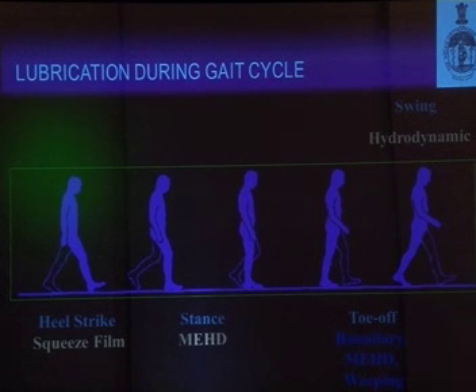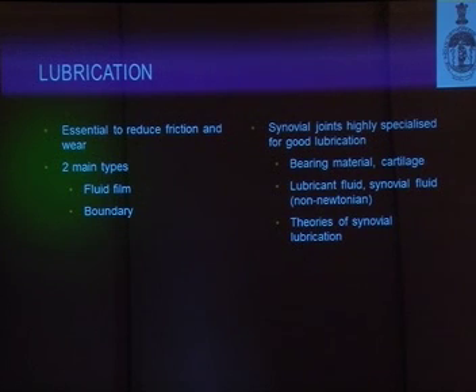If you look at the hydrodynamics during the lubrication in the gait cycle, during the heel strike, which is the first phase, is squeeze film, and during the toe off is weeping lubrication. So in other words, lubrication is essential to reduce friction and wear, and we have two types, the fluid film and the boundary. The synovial joints are highly specialized for good lubrication based on the bearing materials, cartilage, the lubricant fluid, and the synovial joint fluid.